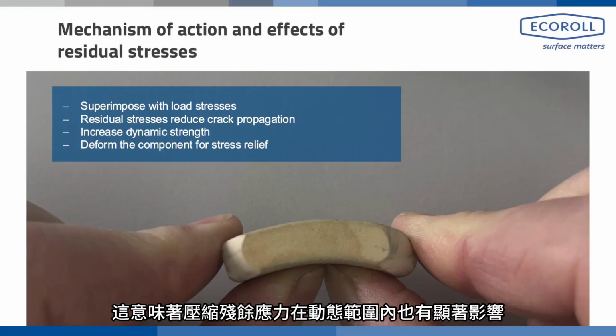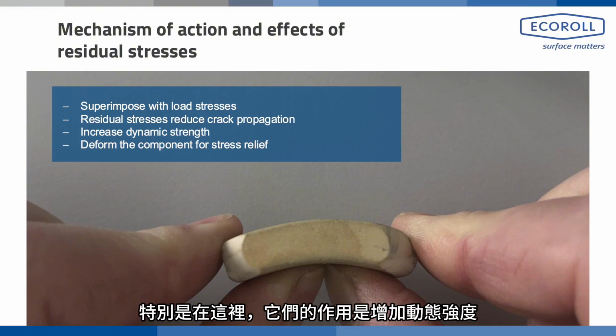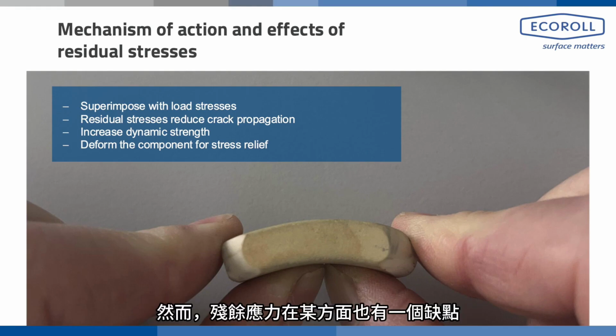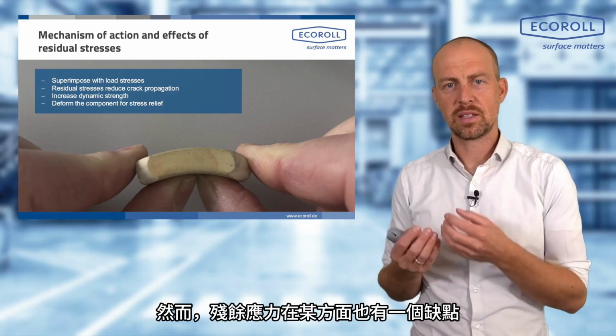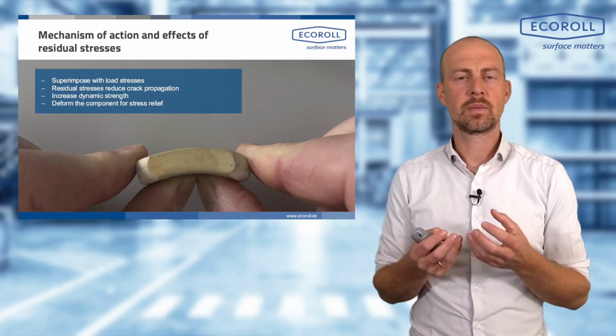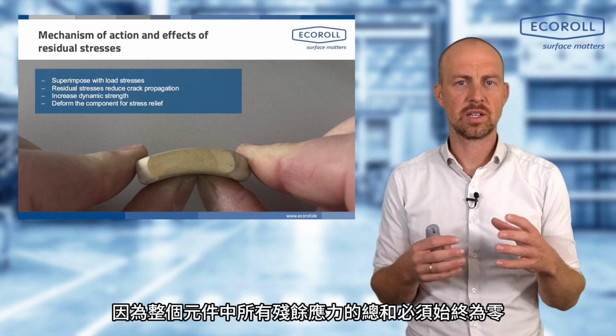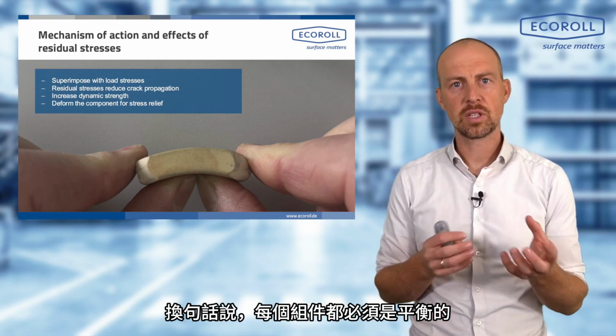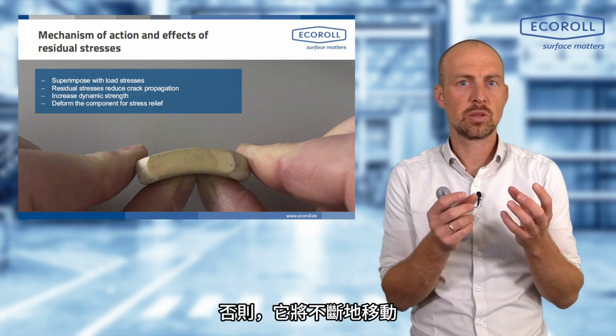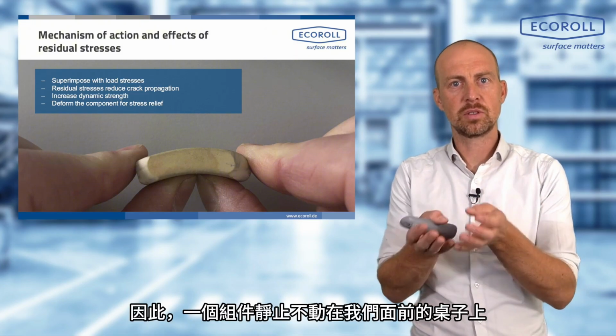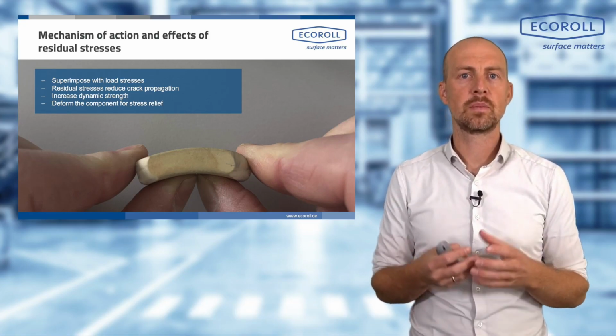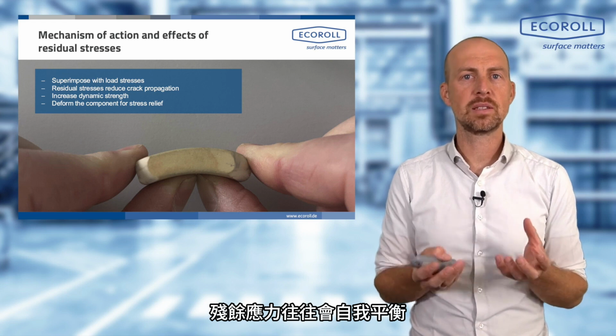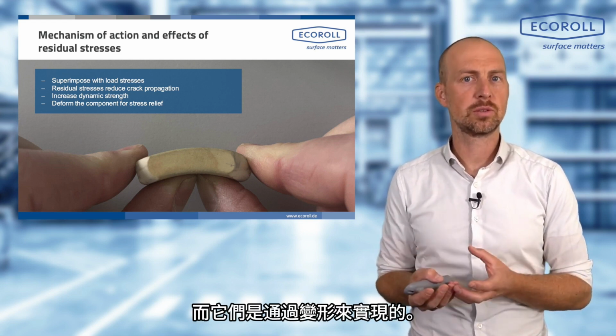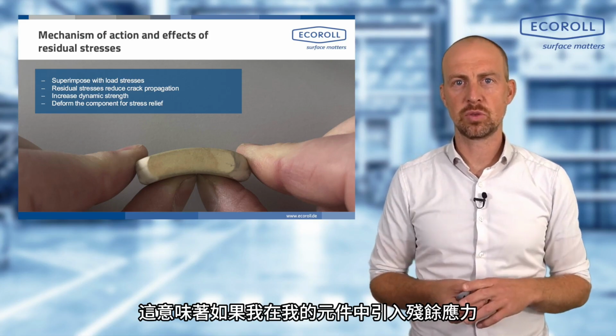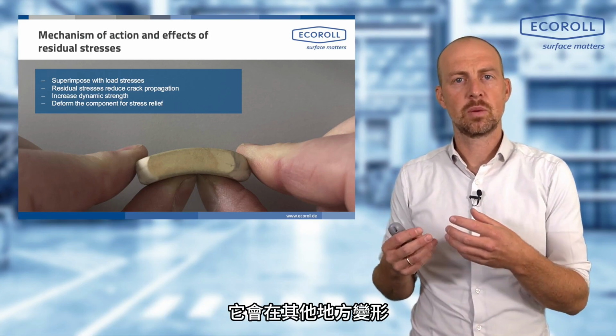This means that compressive residual stresses also have a significant impact in the dynamic range, and especially here, they act to increase dynamic strength. However, residual stresses also have a disadvantage in one respect. Since the sum of all residual stresses in an entire component must always be zero, in other words, every component is balanced, otherwise it would continuously move. So a component sits still in front of us on the table and doesn't move all the time. Residual stresses therefore tend to always balance themselves out, and they do this through deformation. This means that if I introduce residual stresses into my component, it will deform somewhere else.